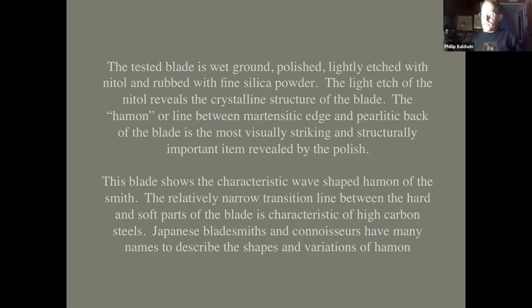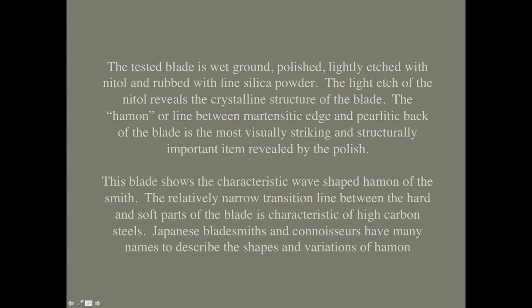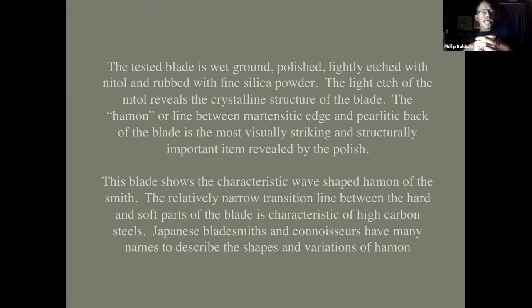In this case, it was made as a kitchen knife. So wet ground polish, lightly etched with Nital, which is a 5% solution of nitric acid in ethyl alcohol. It gives a very, very clear etch and tends to bring out crystalline structure, and then rub it with a fine silica powder, which is to say volcanic ash. Again, this is right out of Japanese swordsmithing or bladesmithing. Next slide, please.